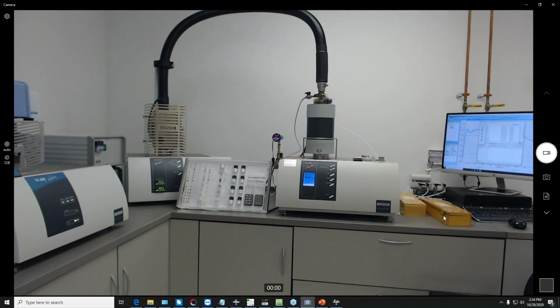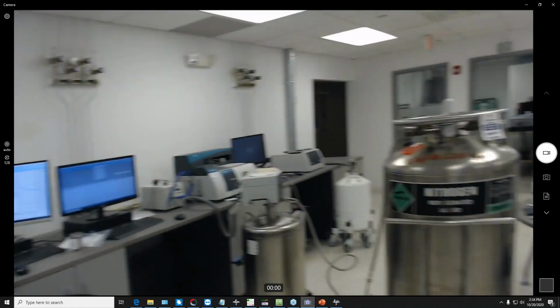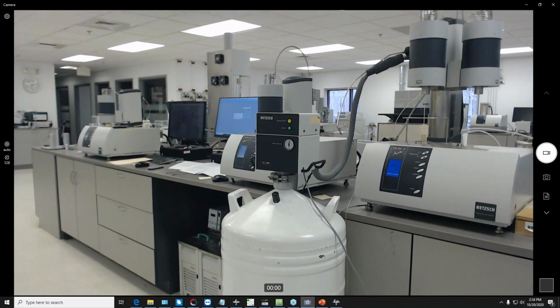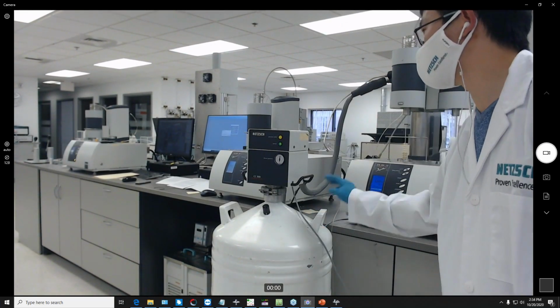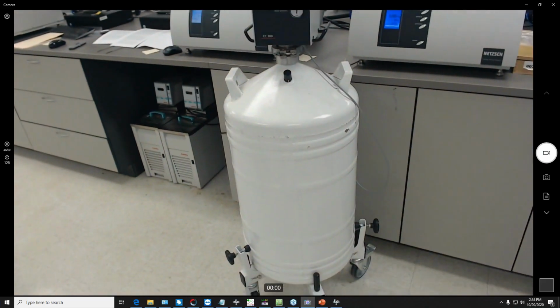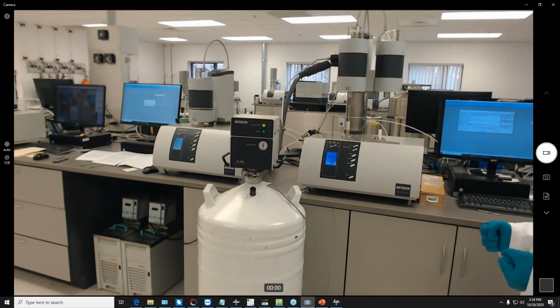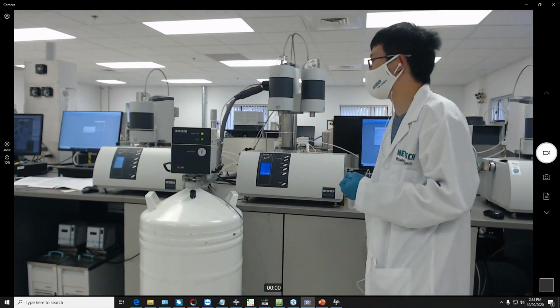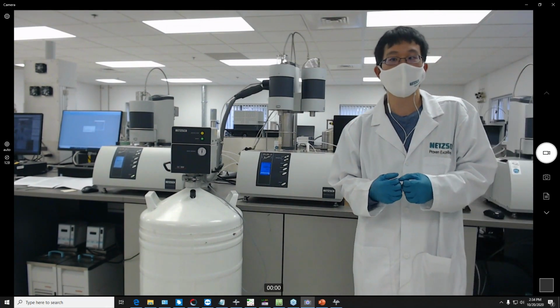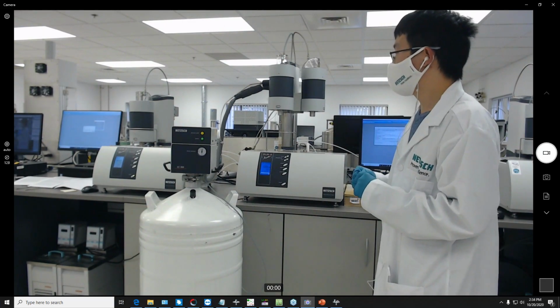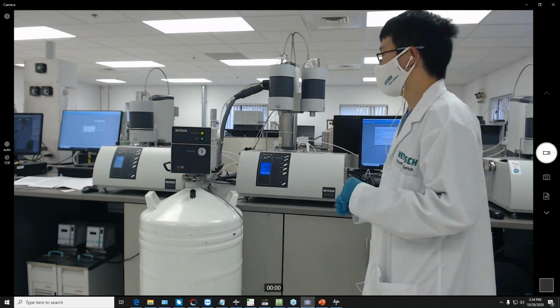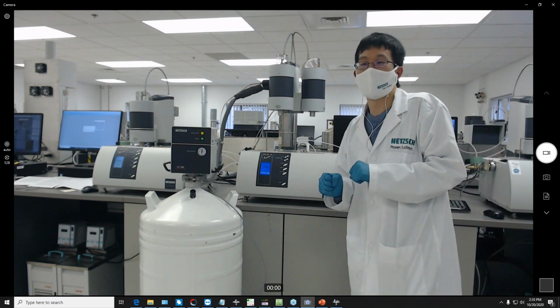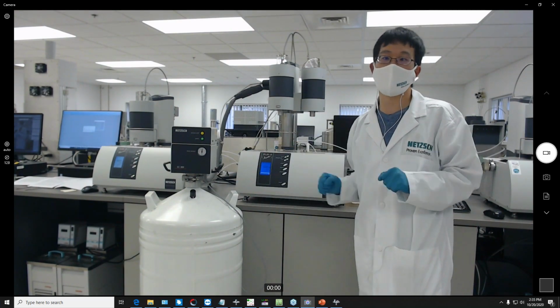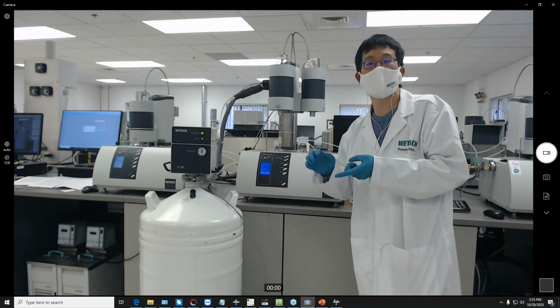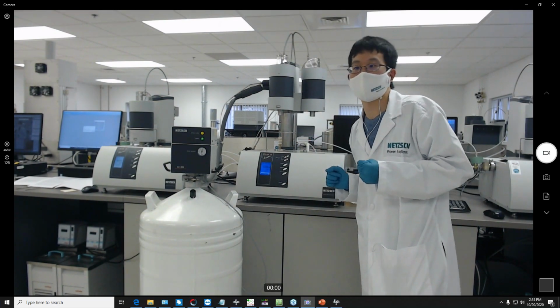For DSC at temperatures less than 0 degrees using liquid nitrogen, I have problems with DSC signal cooling. Let's go over here. For our STAs, usually we'll have a liquid nitrogen dewar attached. Here we have our CC300 unit. Usually, running sub-ambient on our STA units, especially to lower temperatures, we recommend you utilize helium as your purge gas, because helium has a little bit better thermal conductivity at those low temperatures, so you get better signal response and a more stable signal. Also for cooling, because the liquid nitrogen does a pulsing effect, if you want to acquire cooling data on the STA, we recommend you use gaseous nitrogen because it'll do a continuous stream and your signal should be a lot smoother. So the two things I would recommend are to use helium as your purge gas and to use gaseous nitrogen for cooling.